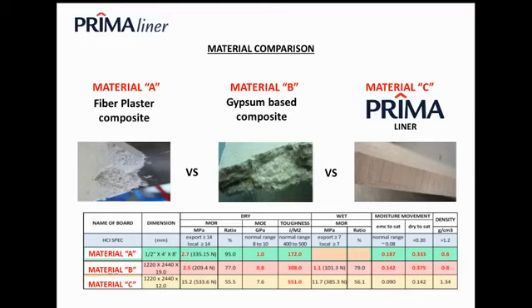Okay. And not only looking at the modulus of rupture, we're also looking at the modulus of elasticity. This is to show how good the material is at bending. Look at material A, it can perform up to 1.0 GPa. Material B is 0.8 GPa, whereas Prima Liner can perform up to 7.6 GPa. So that is a very huge gap. When we talk about toughness, it's also similar in character: 172 joule per meter square for material A, 308 for material B, and material C is 551.